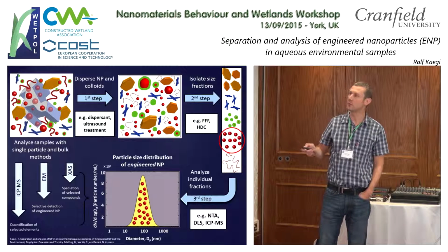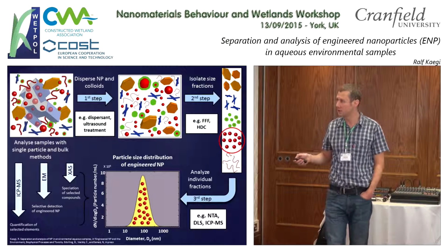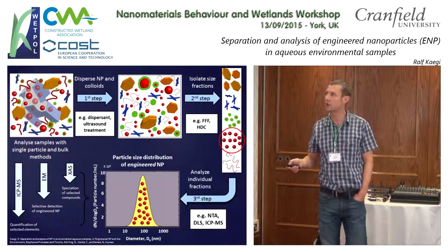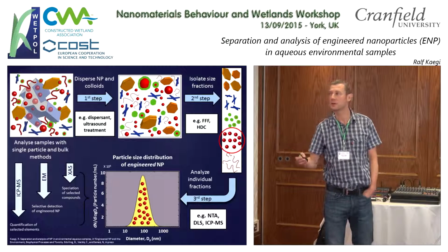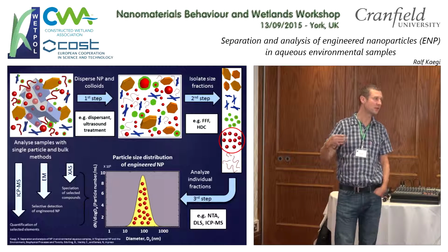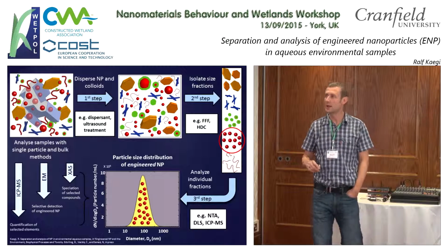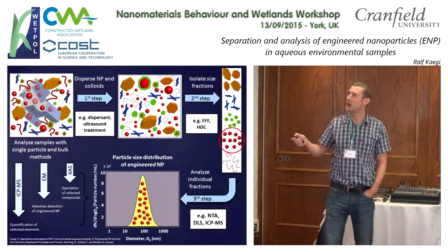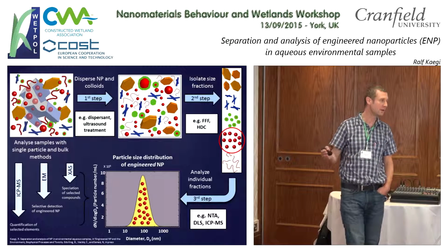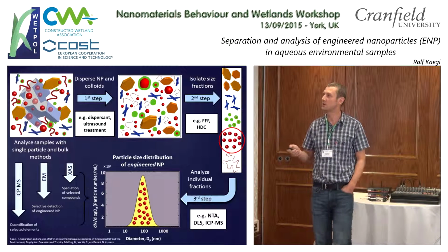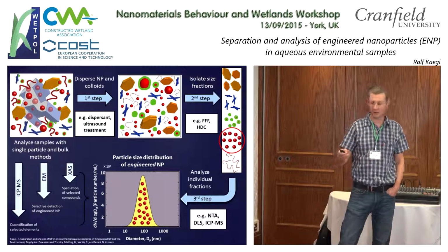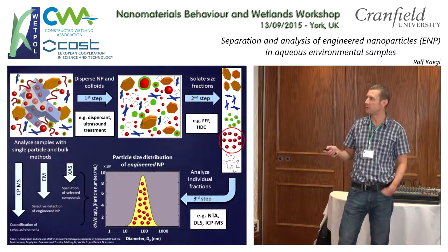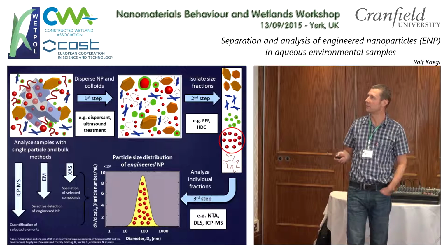This is our system here, the complex system. We can either go clockwise or we can go counterclockwise. Clockwise means that we first try just to disperse the particles using ultrasound treatment, using dispersion agents, using selective dissolution of matrix components. Now we have this system here that won't work in practice, but in theory, as a thought experiment, it is fine. You have well-dispersed particles, and then they have different sizes. And then you need a size fractionation. A size fractionation, you can, for example, use a hydrodynamic chromatography or a field flow fractionation.